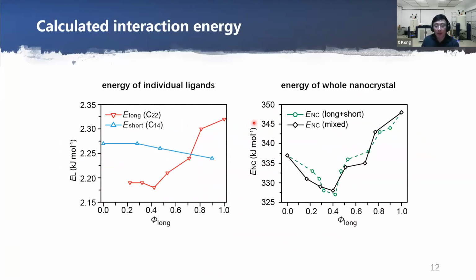So we obtained the interaction energy for the respective long and short ligands. This analysis can be performed on the selectively labeled samples. So like one ligand is protonated, the other is deuterated. So we can see the interaction energy of the long ligand is much reduced for different ligand ratios, especially when they are like 0.4 or 0.5 ratios. But the interaction energy for the short ligands is very much the same. So this is very consistent with our studies with deuterium NMR.